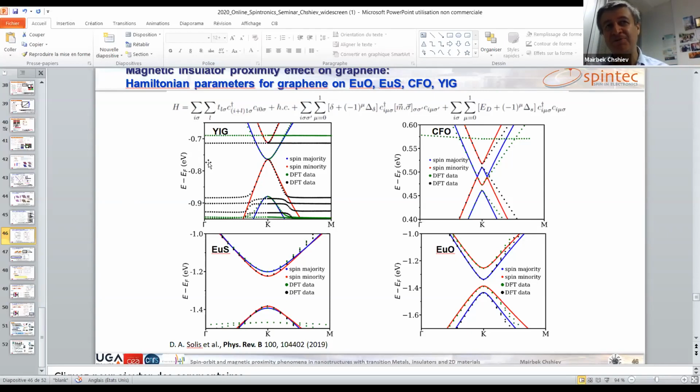And then for anti-parallel, what is the contribution of majority and minority? You will see that within this energy region, where we observe the huge magnetoresistance, some of them will not contribute at all. For anti-parallel situation, it will be completely closed, while for parallel it will be open. So it is a classical spin valve situation from that point of view.